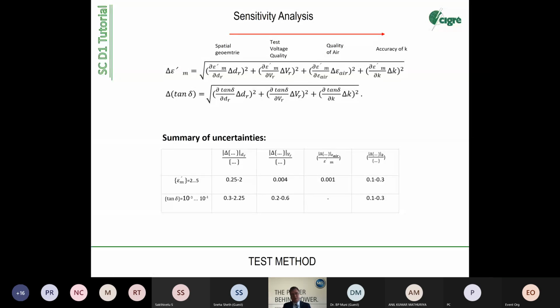And this is also lessons learned for future groups. With this method, you can see qualitative effects. You cannot, or you should not, use them for quantitative analysis. So you can see a trend, you can see a tendency, you can derive from this tendency certain conclusions, but you should not work with absolute values. That was the lesson learned from the analysis. It was a warning here, and it came out in the results exactly in the same way.